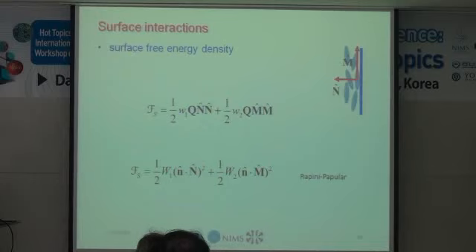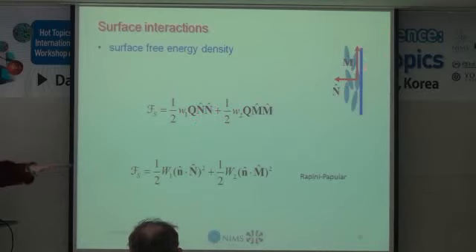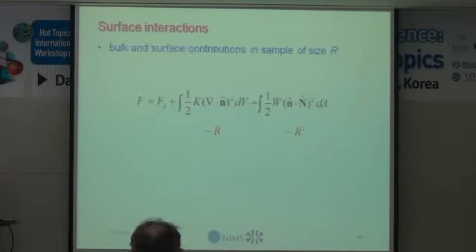All right, surface interaction. These materials have to be bounded by something, and there have to be interactions at the surfaces. Again, arguing from symmetry, every surface has a normal, and we can make a scalar from the order parameter and this normal. In addition, one can treat the surface somehow. One can rub it, for example, or make grooves. Then one will have another direction in plane which is distinguished, and so one can have another scalar term. Writing this again in terms of the director, one has the standard Rapini-Papoular form for the surface energy. So these are the boundary conditions, as it were, for minimizing the free energy to find the equilibrium configurations.